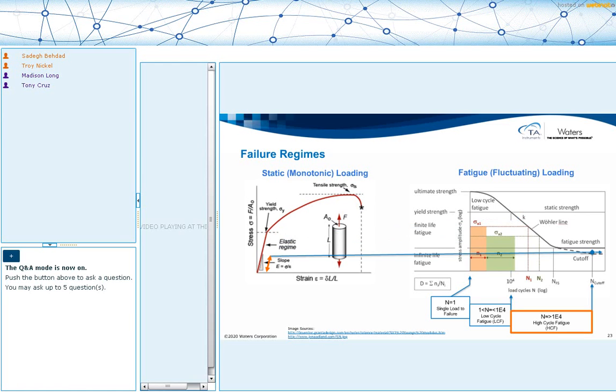So you usually see a point with an arrow pointing to future in time, which is an indication that we know that this material is going to break at some point, but it wasn't within the number of cycles that we studied. We usually refer to that point as the endurance limit of your material. So some materials have it, some don't. Usually the materials like steel and titanium that are used inside your body are chosen to be those who have an endurance limit to ensure that they will survive for a high number of cycles to minimize the need for a replacement or another surgery.